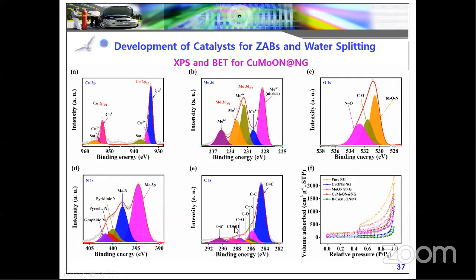You can see before, the initial graphene oxide contains carbon-oxygen bonds, and the C-O peak is of very high intensity. After reduction by high temperature pyrolysis, the bonds are reduced and we get almost perfect carbon-carbon bonds. And from the structural analysis, the BET surface area further confirms our catalyst. Nitrogen-doped graphene has a higher surface area, and when we dope with monometallic copper and molybdenum, the bimetallic copper molybdenum oxide nitride has a high surface area, almost near to the nitrogen-doped graphene.